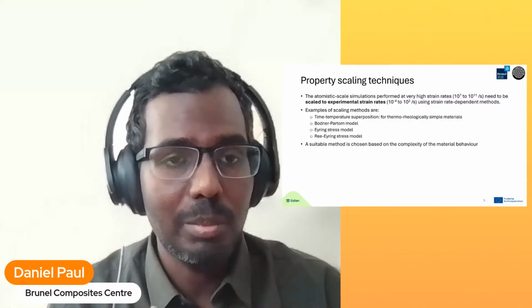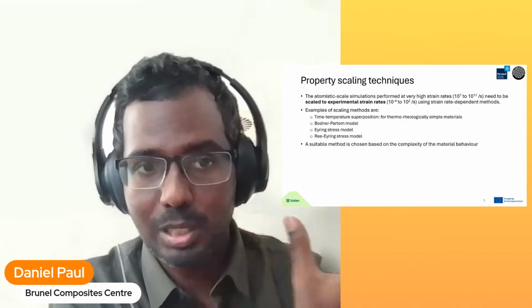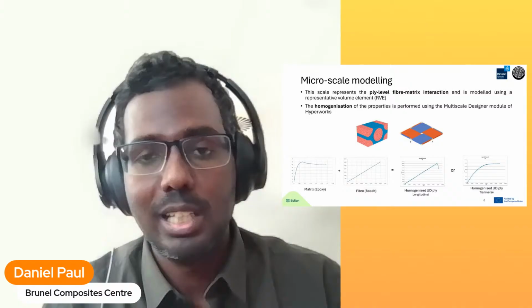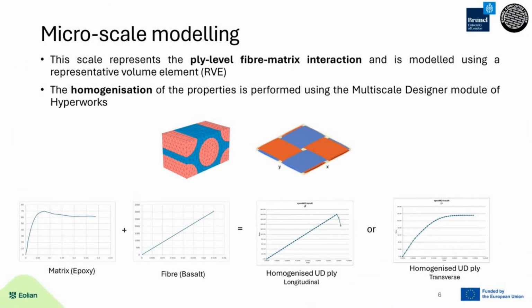Especially in vitrimers, there is cross-linking happening like normal thermosets, but also, as mentioned earlier, there are some bond reactions happening at high temperatures. So at different temperature ranges, we have different properties, different behavior of the material, of the molecular cross-linking. So vitrimers will need complex models to be used to do the property scaling. But once this is done, we have got the properties of the vitrimers or polymers that we are analyzing from the molecular scale modeling and the scaling techniques. So now what we can do is apply these vitrimer properties together with fiber properties, the fiber geometry.